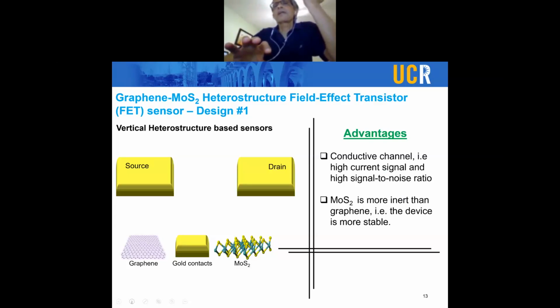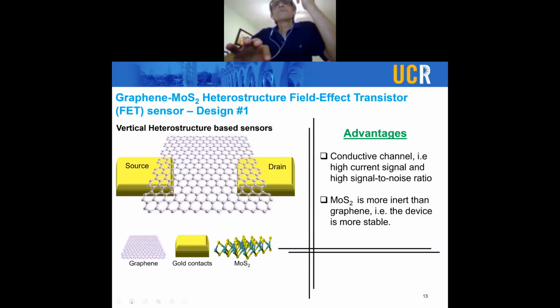The first structure was our naivety and said the simplest one would be to try to take advantage of the conductivity of graphene and put graphene as the underneath layer. Secondly, also when people use graphene as the sensing layer for contaminants in air, there is a big drift of graphene due to the absorption of oxygen and other elements or other chemicals that absorb on the surface of graphene. So there is always a sensor drift. So we thought of, okay, as compared to that, molybdenum sulfide is more stable. So what we will do is we will put the underneath layer of graphene to have good conductivity channel. And on the top of that, we are going to put MoS2. And let's see what happens when we have a heterostructure like this.